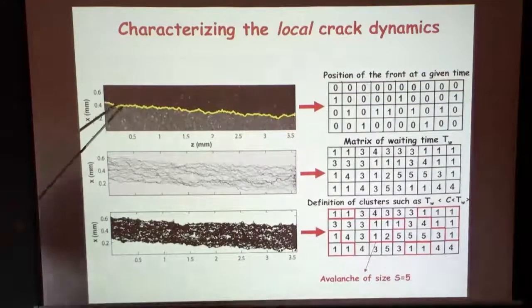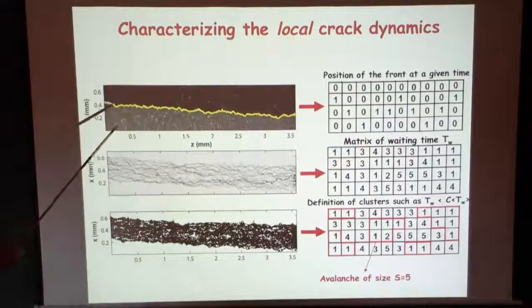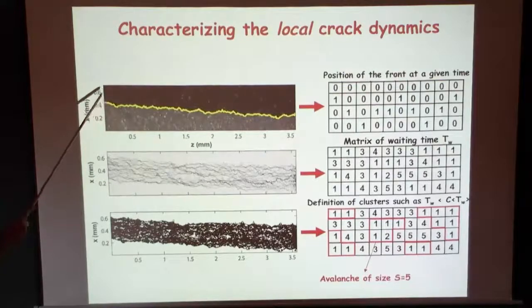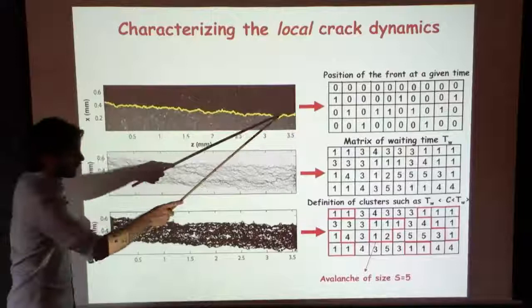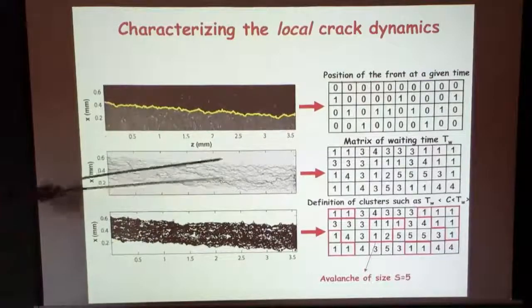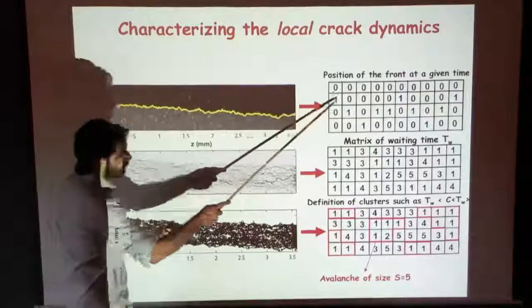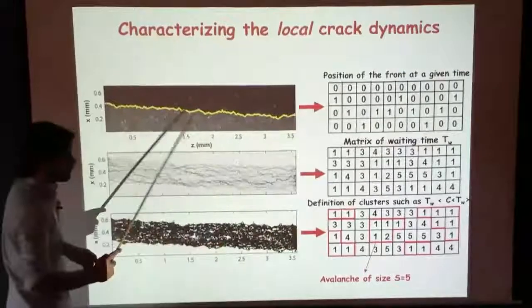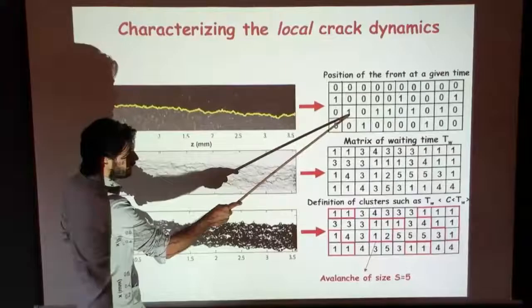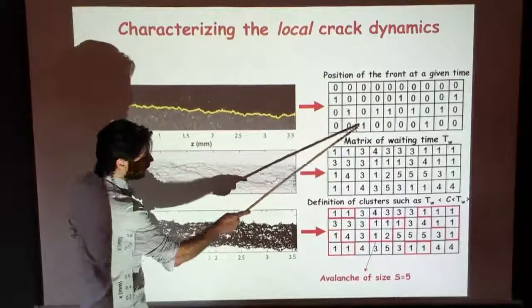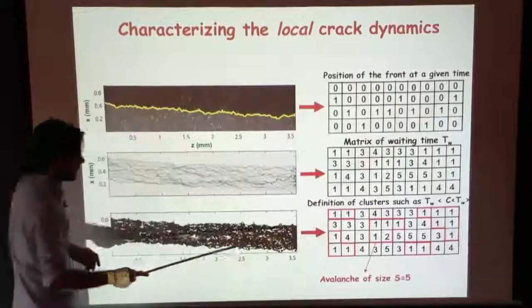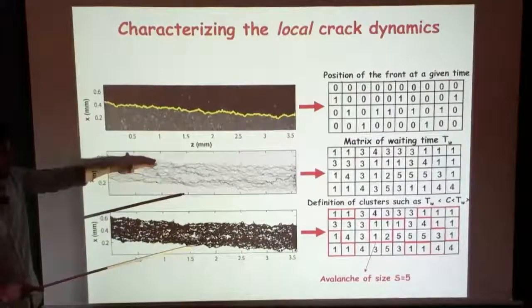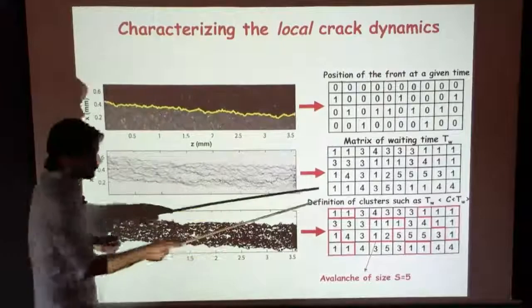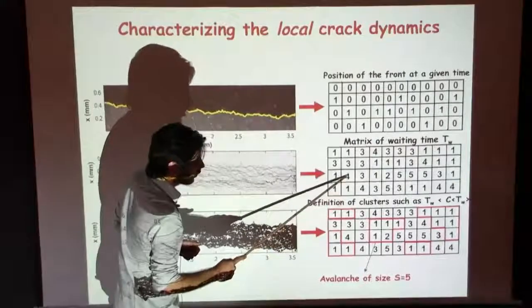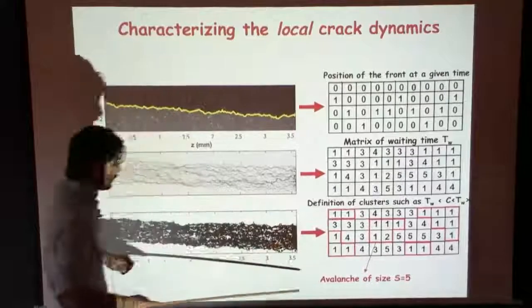This was the idea of Måløy, Stéphane Santucci, and co-workers. For each image, you record the front location, and then you fill a matrix that corresponds to each pixel on each image with the time spent by the front in that pixel. Here there is 1 millisecond spent in each of these boxes, and as you use many images corresponding to different times, you fill your matrix and get a waiting time matrix telling you how much time the front spent in each position.